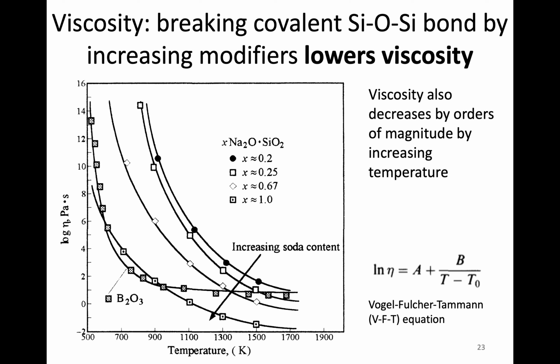So it lowers viscosity. This is log of viscosity as a function of temperature. Viscosity always changes with temperature, but the main thing we see here is that once we increase the soda content, or sodium, we're going down, and that going down means a lowering of the viscosity. That means it's going to flow more and more like a liquid, with a faster response when we modify it and break those bonds. We can model this log viscosity-temperature relationship with this VFT equation that you see here. That's a very common way of seeing the viscosity.